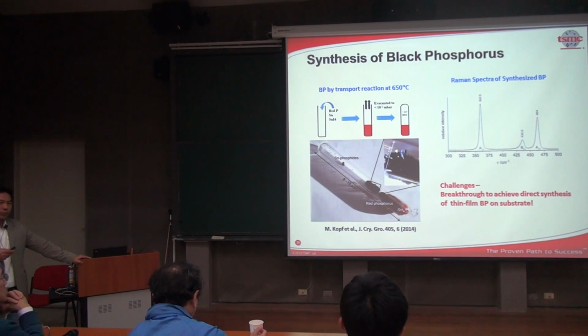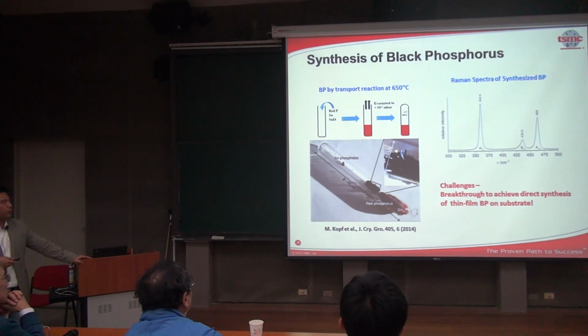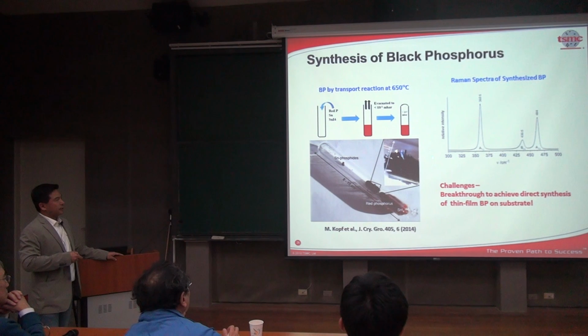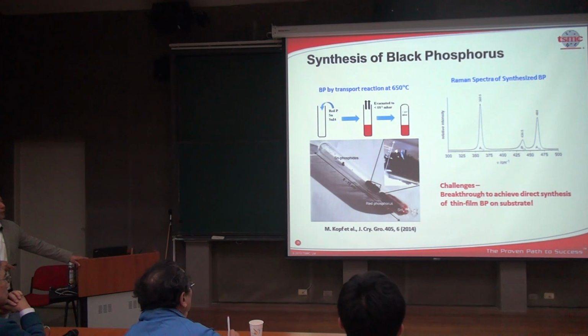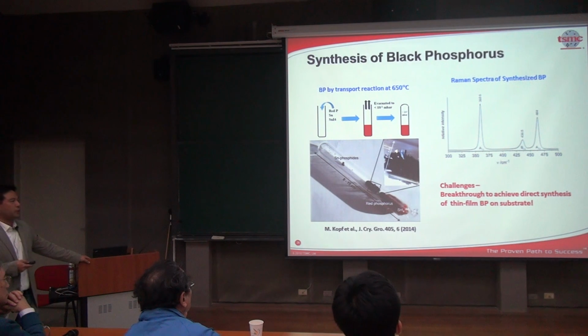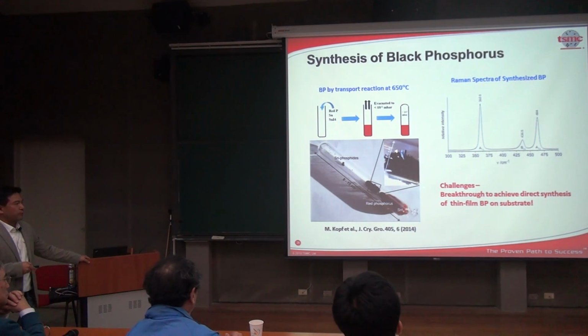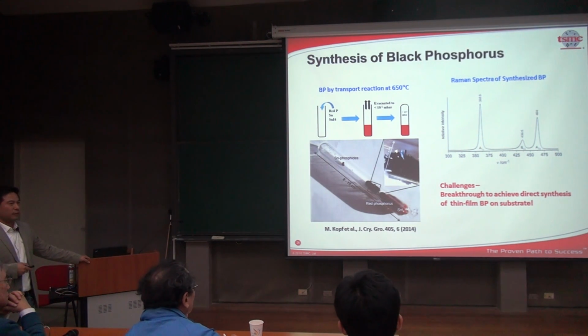Now, below a temperature of 550 degrees C, black phosphorus is the most stable form. So you will form black phosphorus. And it is this needle-like structures that you see here, and you can confirm their existence from Raman spectroscopy. However, the breakthrough is still required to have some direct synthesis. Otherwise, this material will only be of limited use in the lab.